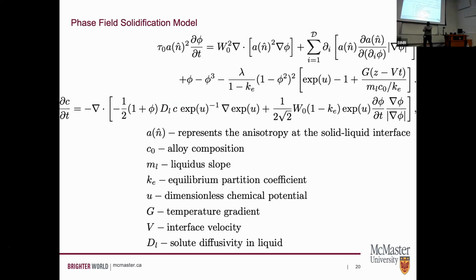This is probably going to be one of my 3 or 4 slides, so let me try to break it down. What I have here is a generic phase field description that tracks the phase, i.e. the order or state of my system, and then concentration. The concentration term has a term that looks like a chemical potential, so the divergence of a flux, and the flux is related to a chemical potential U, and then some other term that tells me how fast the interface is moving and where I should apply certain conditions, in this case, concentration variable.